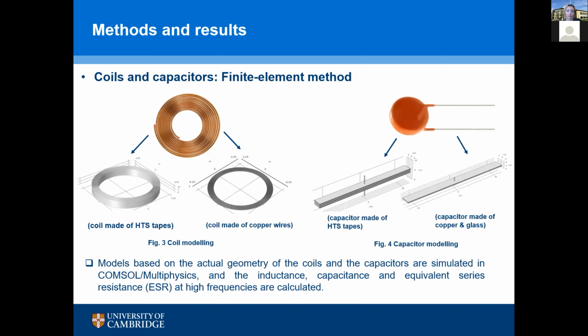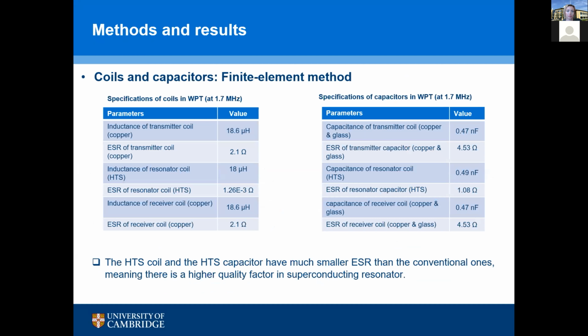Due to the limited access to a lab during COVID-19, we started our research with modeling. Using the finite element method, we simulated the coils and capacitors based on the actual geometry and materials. Inductance, capacitance, and the equivalent series resistance, the so-called ESR, are calculated at high frequencies. Figures illustrate the appearance of models assembled from superconducting tapes and common materials in the software COMSOL Multiphysics. Specifically, we took copper as the material of conventional coils. Meanwhile, copper is also used as electrode plates, and glass is used as a dielectric. The two form a conventional capacitor. For comparison, HTS-coated conductors were utilized to fabricate a coil and a capacitor with the same inductance and capacitance.